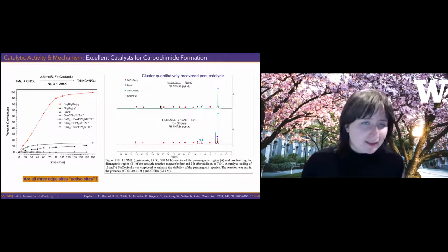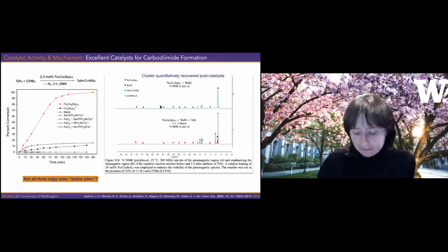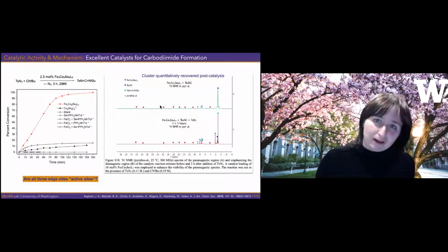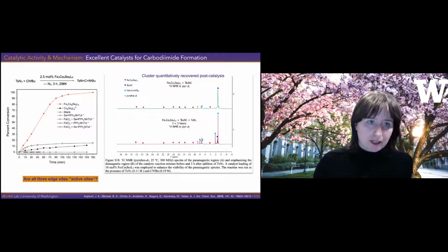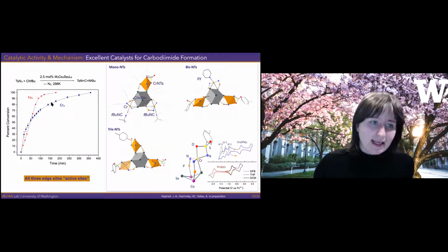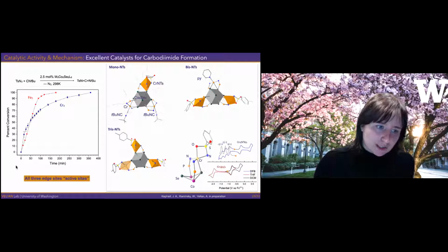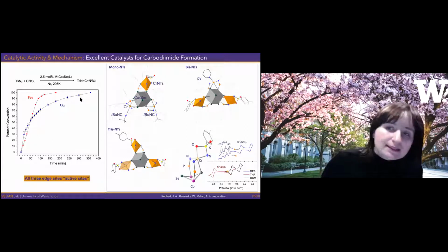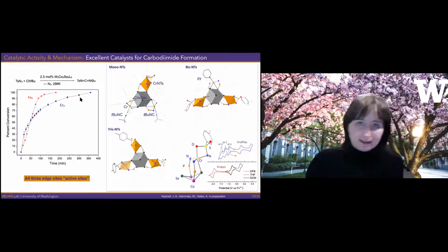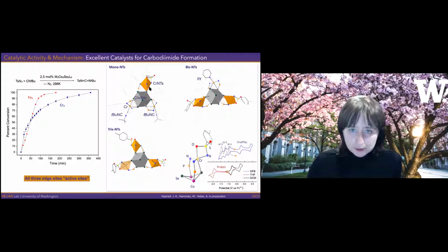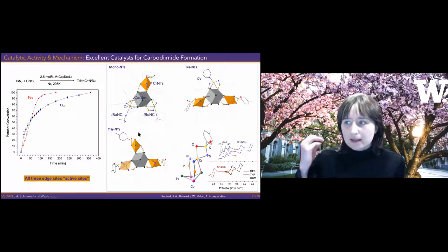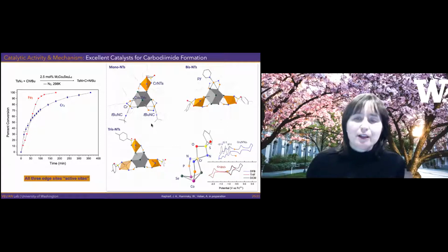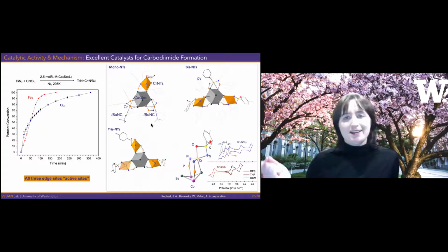So to tackle this, what we did is simply, we thought, hey, if we switch the edge site with some other metal, we might be able to slow down the same transformation. And in fact, that's really the case. If we go from iron to chromium as the edge sites, 3 chromium sites, now we slow down the catalysis. This is just percent conversion versus time. And what this metal enables us to do is to isolate and characterize, these are X-ray structures again, the catalytically potent intermediates in this transformation. And so answering this important question of, are all the edge sites catalytically active?